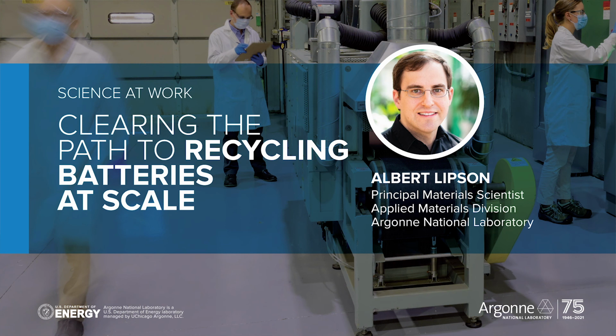We need to figure out a way of separating these. And so Michigan Tech actually came up with this idea to use a mineral processing approach called froth flotation to actually separate these materials out. In this process, what you essentially want to do is you add different types of collector materials that change the surface chemistry of the particles. You want to make one hydrophobic and the other one hydrophilic.